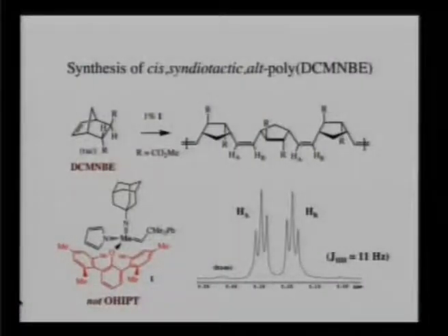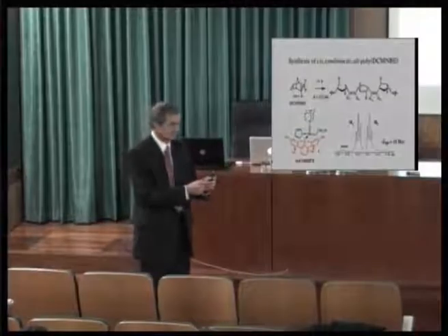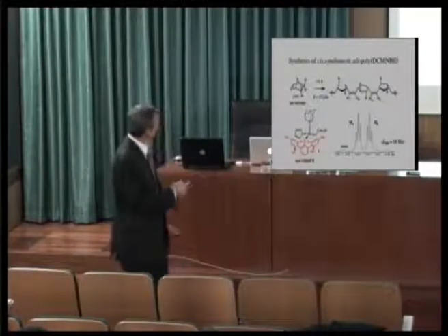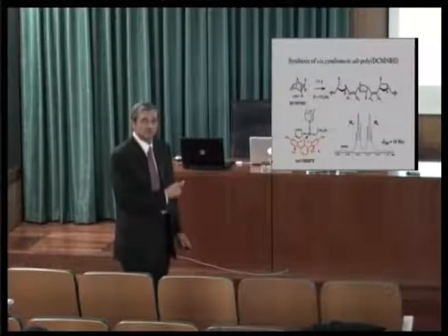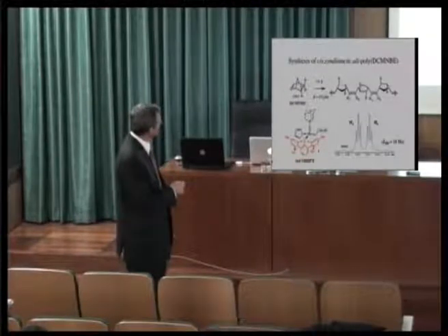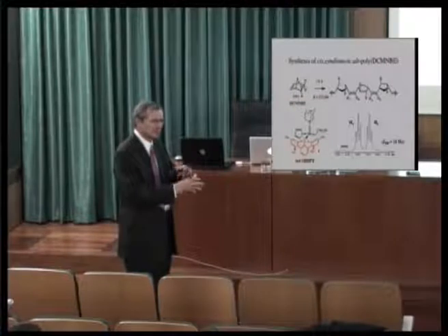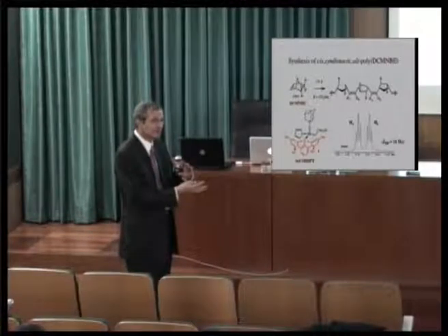At one point, it was about 3 months ago, I had this eureka moment when I thought, well, if the chirality at the metal switches in a polymerization reaction, and you have a racemic metal catalyst, and you have a racemic monomer, then there should be one diastereomeric combination that is favored.